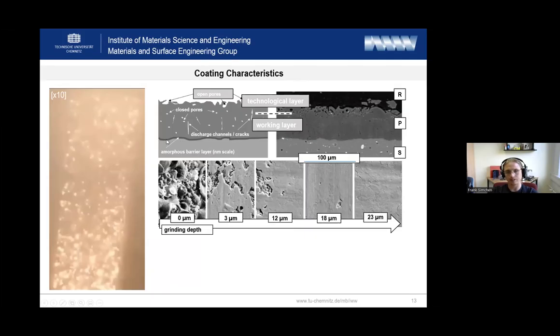So the electrochemically formed barrier layer is still detectable in the resulting coating, because with every spark discharge or with any alternating of the pulse, we create a new amorphous barrier layer, but it's just on a scale of some nanometers. So this you will not see directly in the SEM graph.